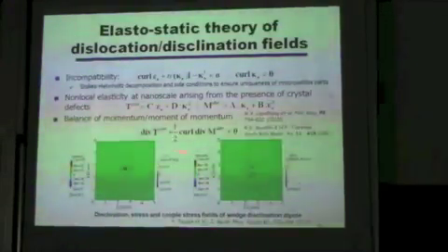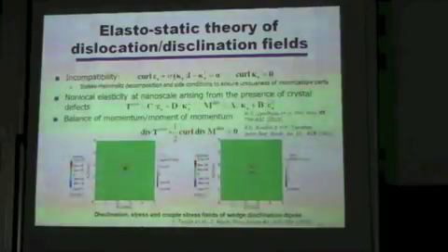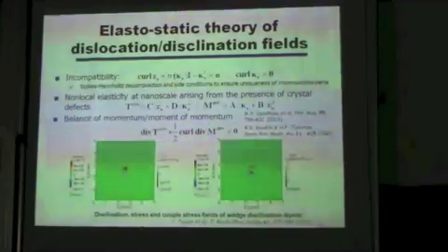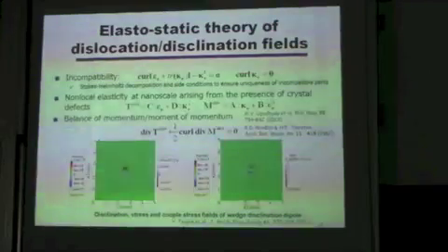So the skew symmetric part actually is here. And in this expression, the curl of the divergence of the couple stress tensor, actually not exactly the couple stress, but only the deviatoric part of the couple stress is here. The hydrostatic part disappears in the equation.